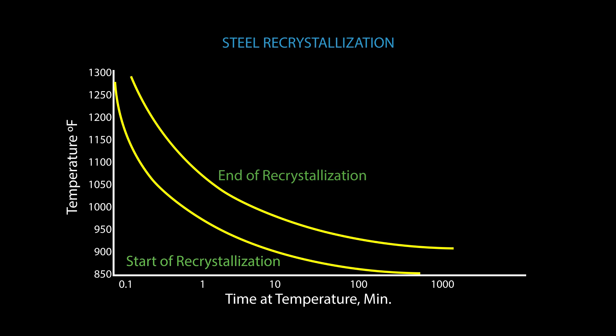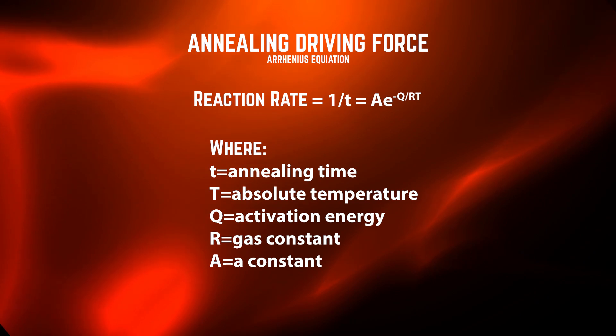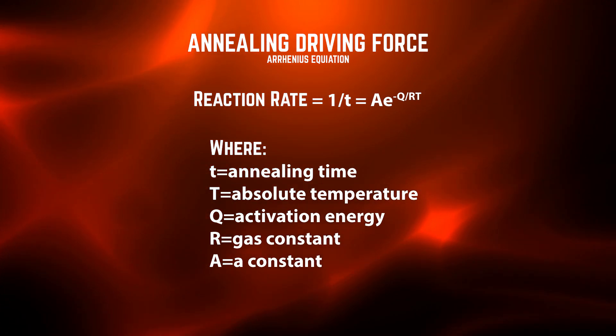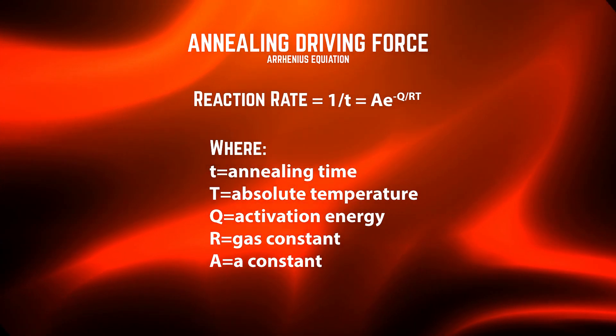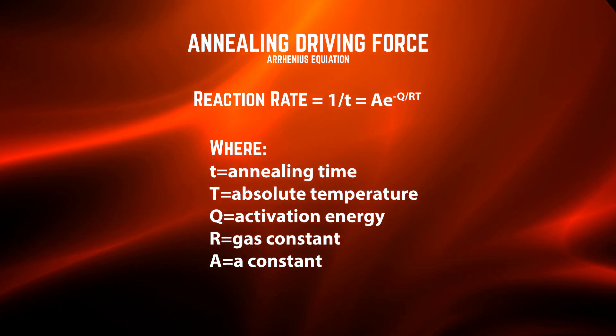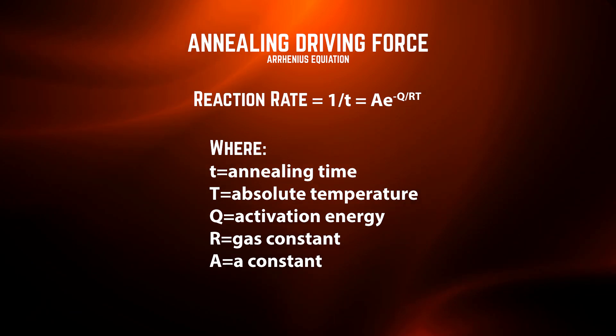As you can see, there are two curves — one for the start of annealing or recrystallization, and one for the end. These are not linear curves, so it's very difficult to predict other times and temperatures with this mode of plotting. So, if you want to determine the annealing time for a certain annealing temperature, this particular equation — called the Arrhenius equation — applies to every single material being annealed, where t is the annealing time, T is the temperature in degrees Kelvin, R and A are constants, and Q, or activation energy, is the driving force that has to be overcome for the annealing process. Using this equation, if you plot it, the annealing process can result in straight-line curves.